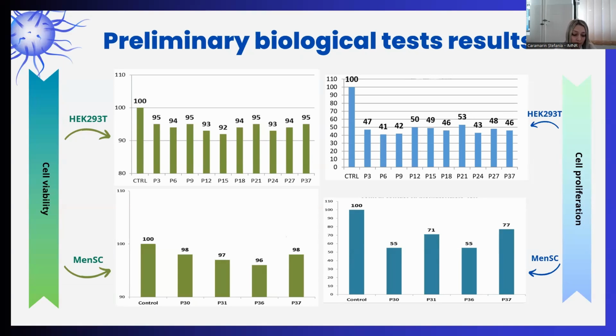For the cell viability analysis, the number of living cells that are not stained by trypan blue was expressed as a percentage of the total number of cells counted for each sample, and then reported as a percentage of the control viability, considered as 100%. And looking at the graphs on the left side, we can see that both cellular lines have a viability very close to the control, between 92 and 95% for the HEK lines, and between 96 and 98% for the MenSC cells.